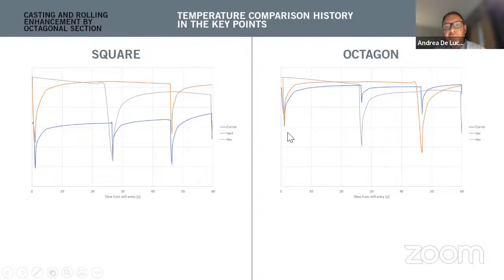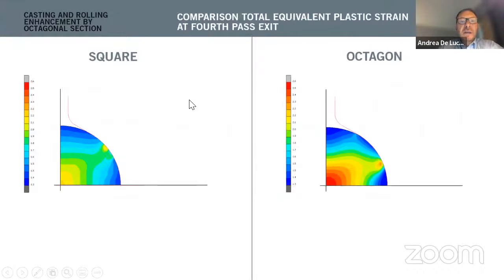This is a summary of the situation. In one case, you can typically have 150, 200 degrees of difference between the shell, the external surface, and the inner part. In the octagon, this difference is less severe. So the quality of the rolling passes is improved. Not only that, with this octagon configuration the rolling and the temperature have a major benefit also on the inner part of the material, where we can obtain an improvement in the grain size.